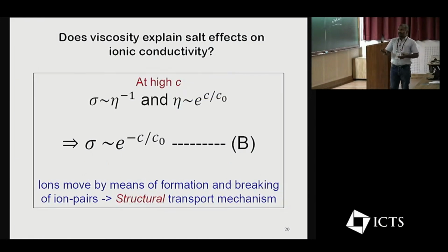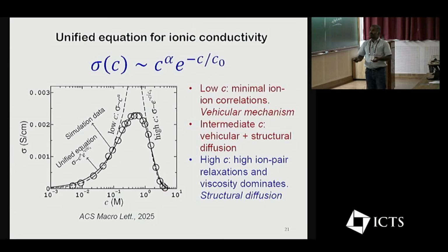And at high concentration, as we have just seen, conductivity goes as 1 by eta, and we also saw eta increases exponentially, which means conductivity goes as exponential minus C. So by combining these two effects, we proposed a slightly modified version of the existing unified equation, C to the power alpha times exponential minus C, which explains the conductivity over a broad range of concentrations satisfactorily.